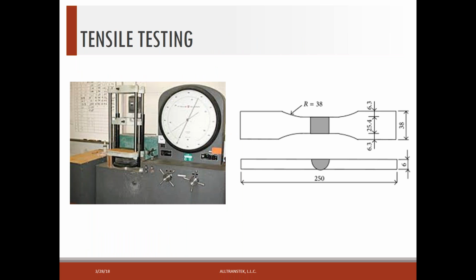Okay, here's a picture on the left of a typical tensile test machine. And then on the right, we have a reduced section tensile specimen outlined. The usual requirement for a welding procedure qualification is to have two tensile tests pulled. And of course, the weld, which is shown in the dark area on the right side of the drawing, you can see how that specimen is reduced in the center. The reason for doing that is we want to make it fail preferentially in that area. We don't want it to fail somewhere outside of that area. So the tensile strength would have to be at least that of the base metal. So that's a requirement for the reduced section tensile.